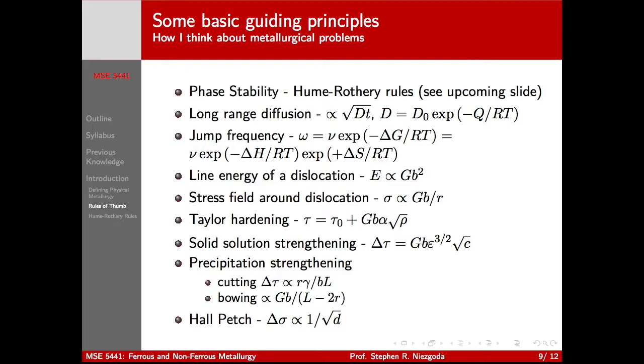Solid solution strengthening. If I have a single phase alloy, my change in yield strength is going to be proportional to two things: the square root of my concentration and the effective strain around the solute atom. How big of a lattice distortion do they cause? So when I say simple physical pictures, that's what I mean. When you have exam questions, those are the key things. What's in this equation? What does it mean? It's more important than being able to spit out that exact equation.